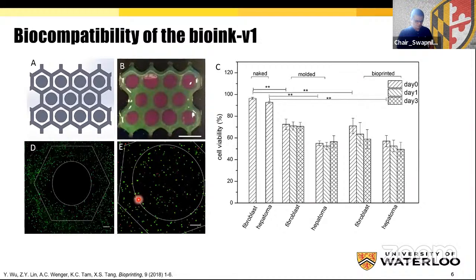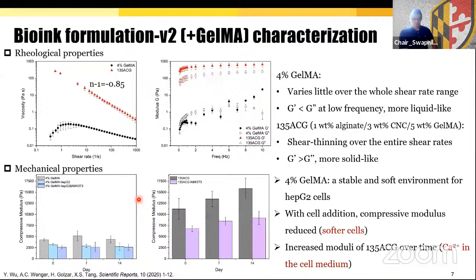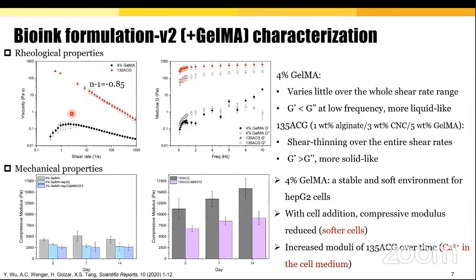There is an ever-growing amount of evidence reported in research literature that GelMA is effective in promoting the cell attachment due to its RGD tripeptide sequences, which are the major integrin binding domains present within extracellular matrix. So we developed our second version bioink that is 1% alginate, 3% CNC, and 5% GelMA, and the pure 4% GelMA. We studied the rheology as well.